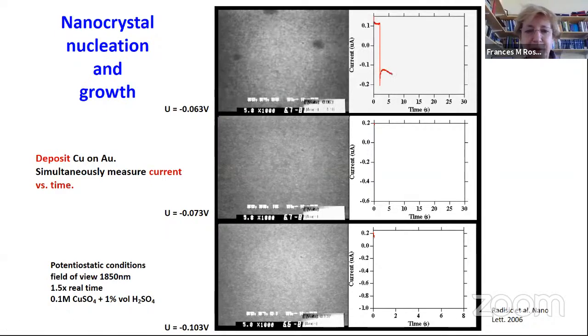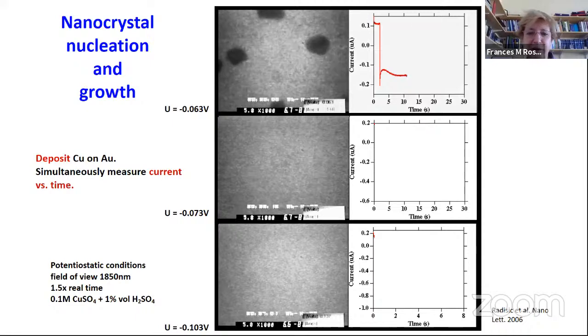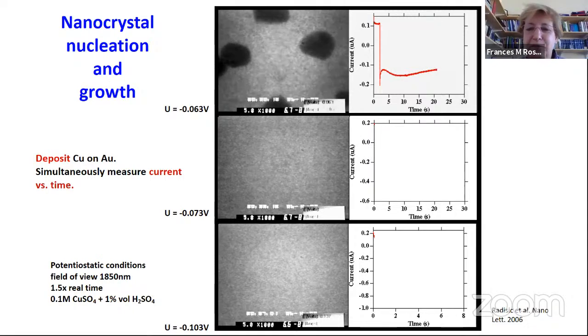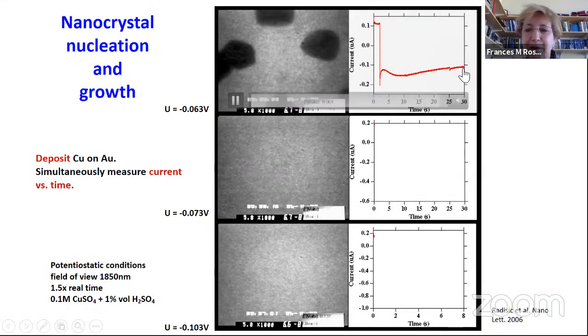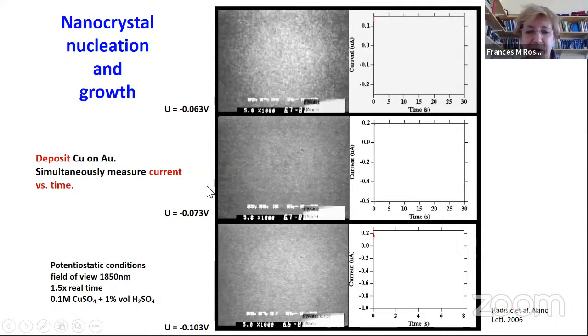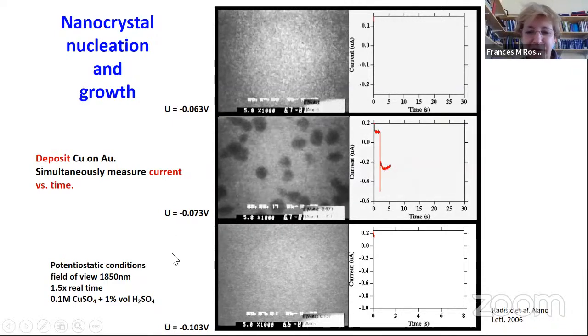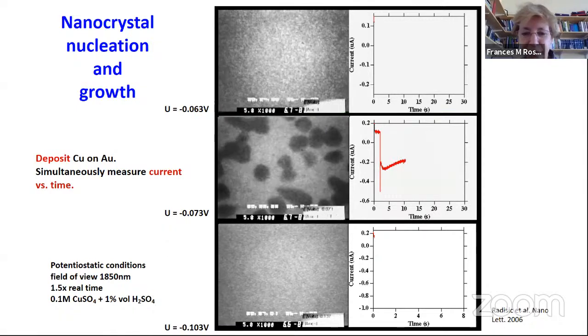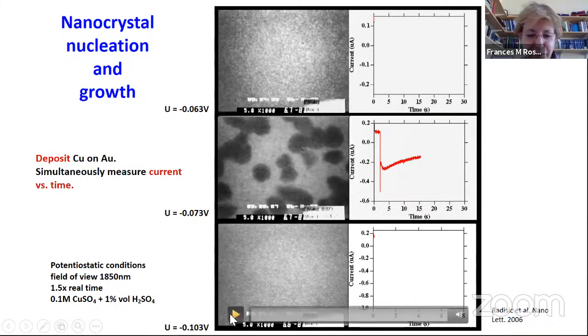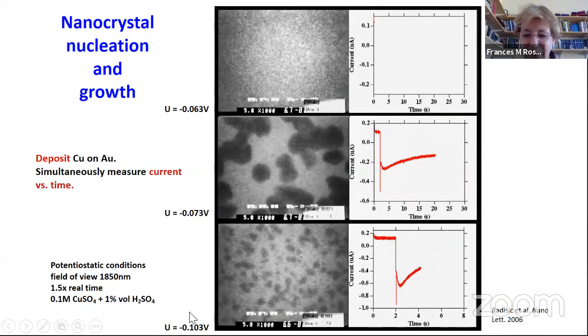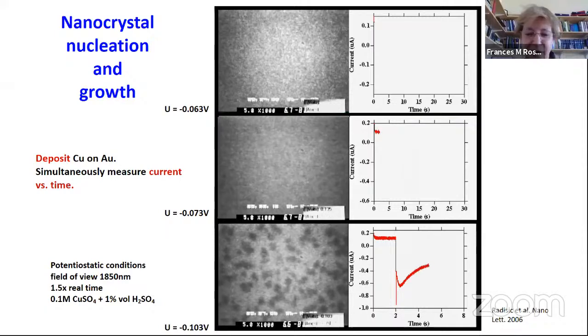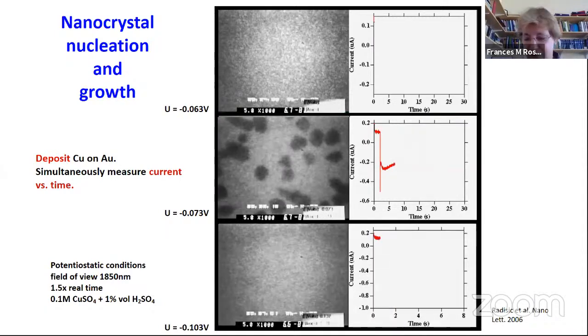This is the movie I showed at the start. You can see nucleation and growth of individual copper islands, while you simultaneously have the current time graph. The current transient has the behavior we expect. It has a peak and then a decay. If I apply a higher, more negative potential, I should say, you get a higher density of smaller objects, and the reaction takes place more quickly, within a few seconds. And then if we go to a massive 103 millivolts, you can see a really high density of small objects, and the whole reaction's pretty much over in a few seconds. So this would be hard to do, you can imagine, in a scanning probe instrument where the reactions take place over such a short time scale.